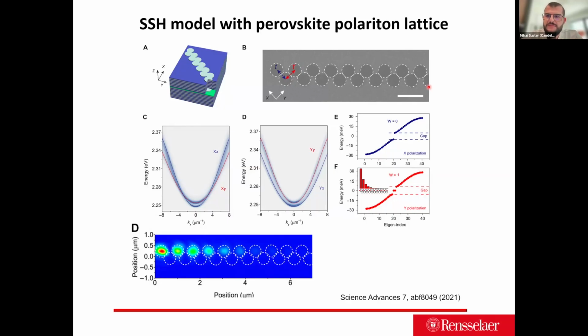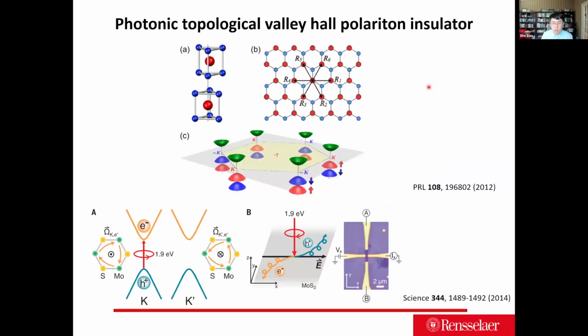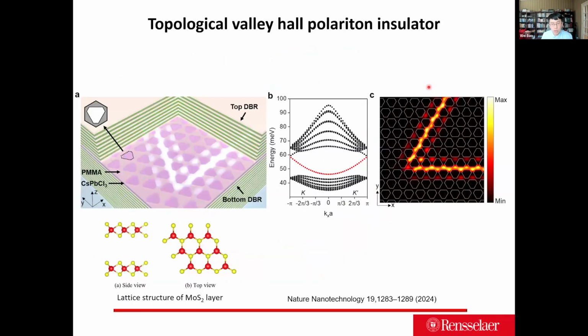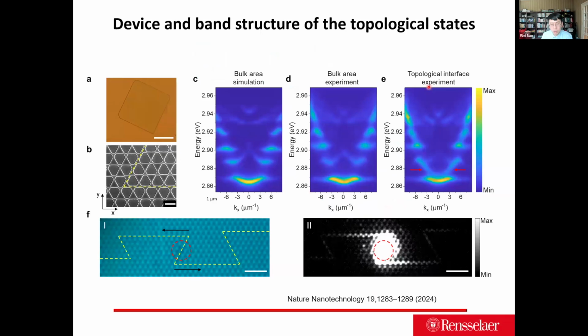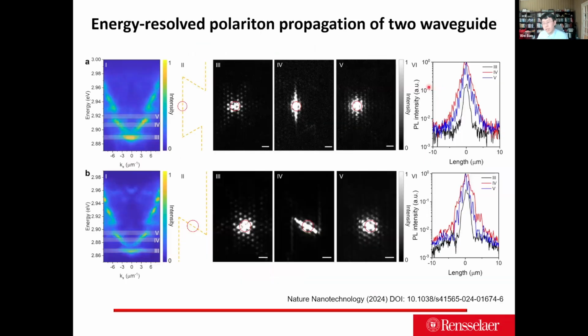Next question. Do you see any changes in the beam's shape during edge propagation? If yes, what is the longest distance with undisturbed beam propagation? Yeah, for our case, I think the propagation length you can extract from here. The main reason the propagation length is limited is not perturbation. It's because we have a gain and loss system. In the polariton, its nature is gain and loss. So if you don't pump it to become gain, where the polariton mode starts to propagate, it will become loss. So it's not scattering, but loss.